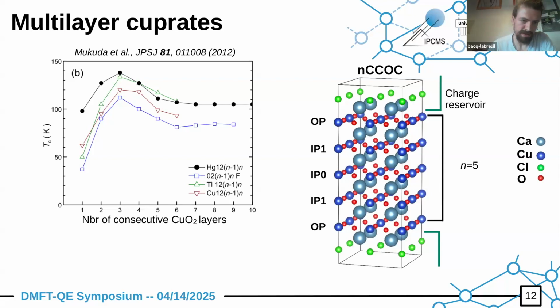So you have this plot on the left, which shows this universal trend where you have critical temperature on the y-axis versus the number of consecutive planes on the x-axis, and you can see that the Tc is always maximum for the tri-layer compound, so n equals 3.